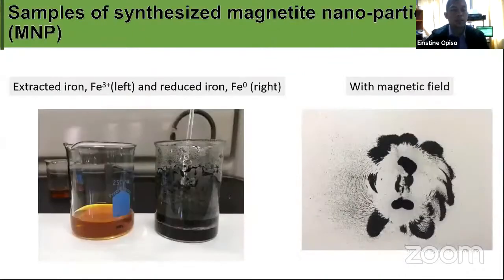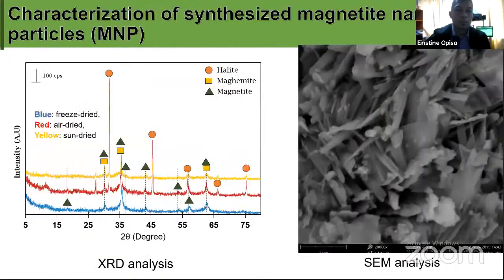So here are some of the photos during our synthesis process. On my left side is the photo of the extracted iron and elemental iron. While here on my right side are the magnetite samples that we have synthesized, subjected to a magnetic field. After that, we also characterized the synthesized magnetite nanoparticles using XRD analysis and SEM analysis.